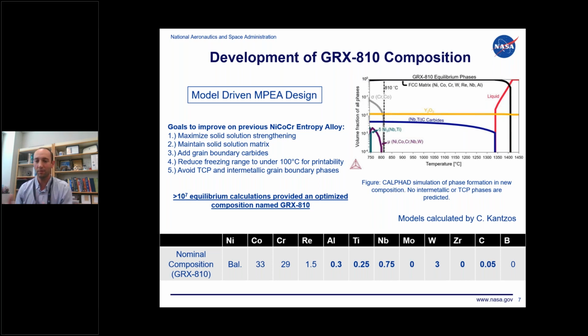So what we find is that a loose rule of thumb is that if your range between the liquidus and solidus temperatures goes above 100 degrees Celsius, you're more likely to run into 3D printing issues like microcracking. So we wanted to keep a narrow freezing range, and avoid TCPs or any intermetallic grains that might form on grain boundaries that would be detrimental.